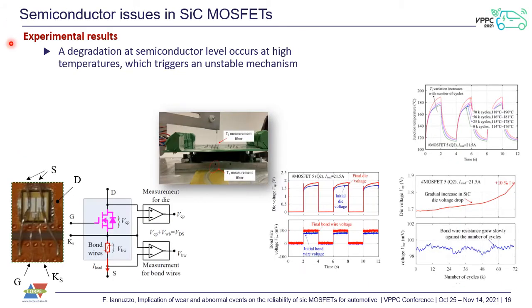All right, the second challenge, in my opinion, is at the semiconductor level. What happens? This experimental setup shows a little bit what the phenomenon looks like. In this case, we used a commercial silicon carbide MOSFET module, and we measured separately the voltage drop across bond wires and the voltage drop across the semiconductor. This is possible because we use power cycling, which is intrinsically made under low voltage conditions, so no need for high voltage isolation. We could use the intermediate connection, which is called the Kelvin source, which is very typical of silicon carbide MOSFETs and MOSFET modules, because this way the gate driver performs better in terms of EMI and also in terms of reduced stray elements of the gate loop.